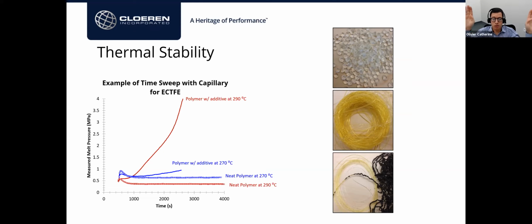Now, the customer was definitely having too much flow at the edges. What we were looking at is basically trying to explain why this was happening. And the explanation, even though it wasn't a complete proof, was that when we changed the parameters to a higher melt temperature and a change in the material viscosity for some reason, we were able to recreate their issue. And from there, the next step will be taken, which would be either trying to fix